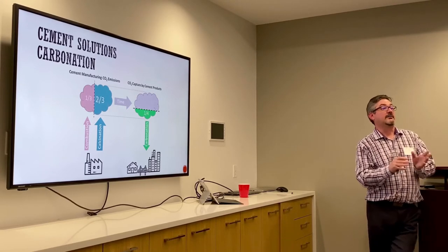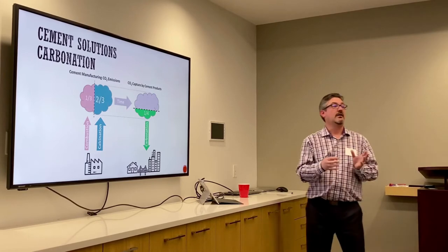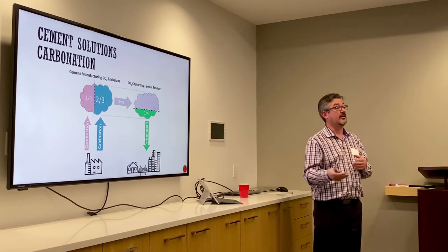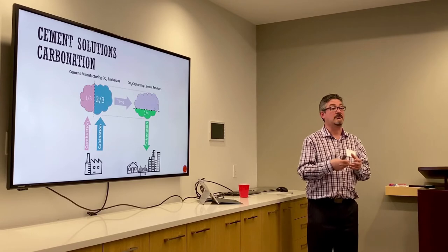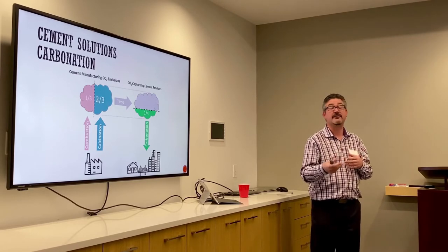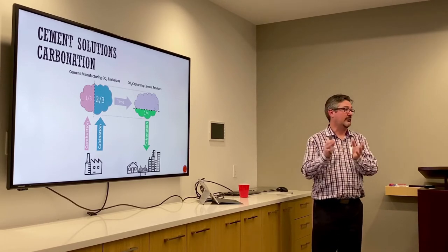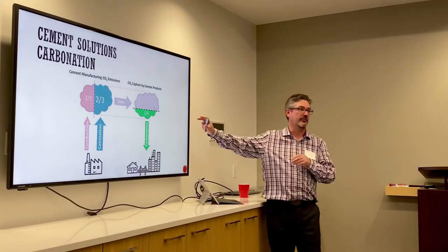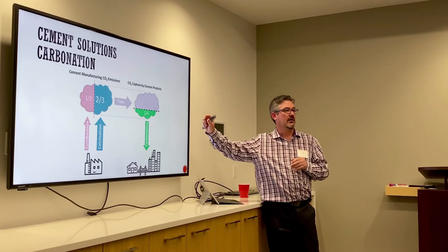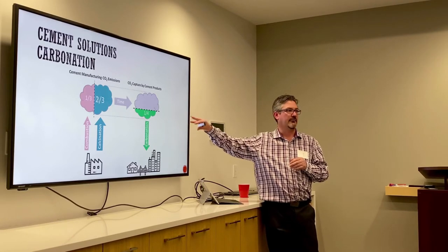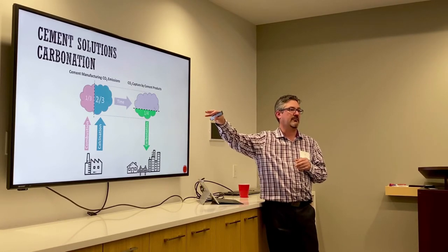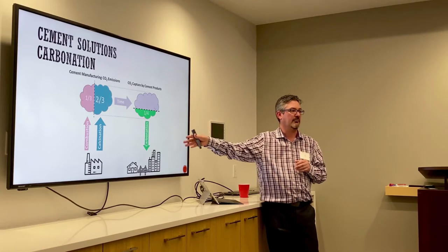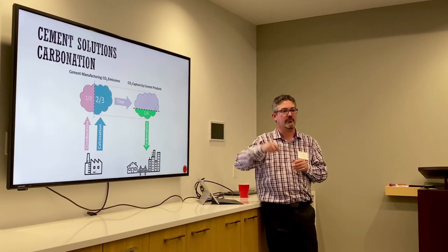And there are a bunch of different ways of measuring this, different research that is still ongoing as to how to measure this and accurately calculate this. But depending on what systems you use for measuring this, between a quarter and a third of the total CO2 emissions from cement manufacturing get reincorporated back into the concrete once it's in place through this process called carbonation.